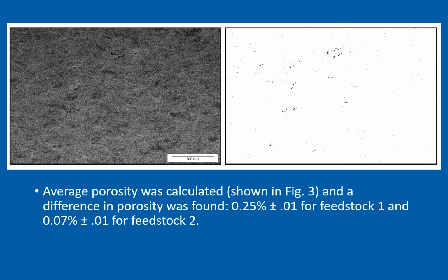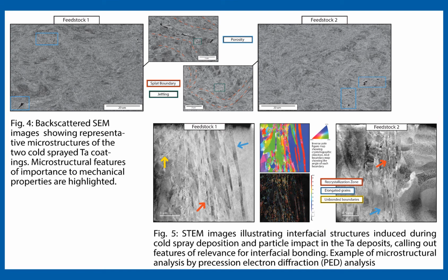Average porosity was calculated through image analysis of backscattered SEM images, and a small difference was found. Backscattered SEM imaging was used to identify and map microstructural features within the two coatings, while PED data was used to characterize the boundaries along particle-particle interfaces as a function of misorientation. However, no clear differences were observed between the two coatings.